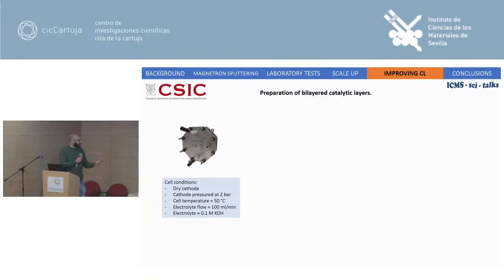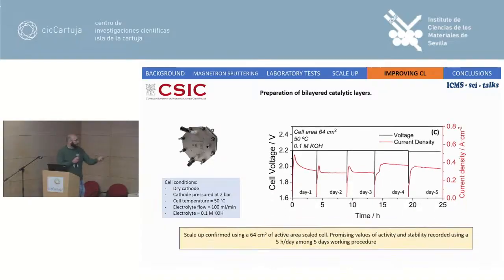So the final test was to prove it in our small prototype, and we tested by a continuous working methodology at 0.5 ampere per square centimeter of current density. We can see how, by working 5 hours per day during 5 days, our system is stable even though the current increased from the 4th day, and we have a very stable behavior with a good value of voltage.